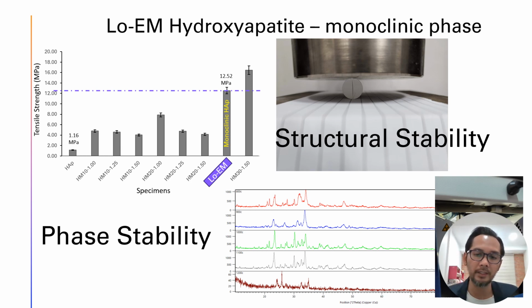Okay, and then we can also see the transformation of the phase. We found that at this specific recipe, when we sintered from 800 to 1200 degrees Celsius, there is a significant phase transformation. Especially at 1100 and 1200, it starts to fuse to form a glassy phase, where we can find noise in the XRD spectrum.